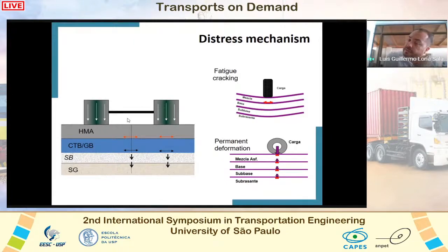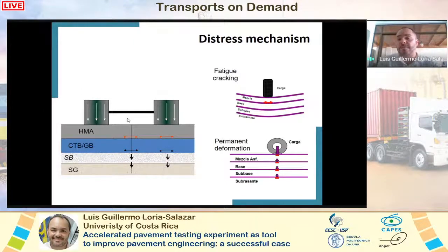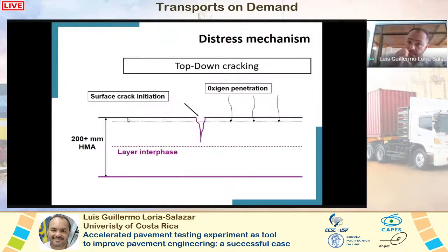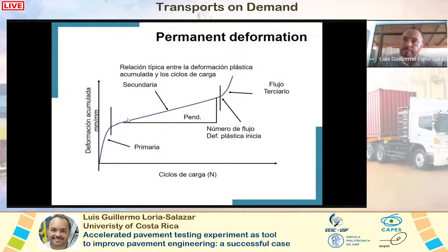We know the various distress mechanisms for fatigue cracking. Basically the bottom-up one, when you have the maximum strain at the bottom of the hot mix asphalt layer. For the cement treated base, you might also have the analysis of the tensile stresses at the bottom of the CTB, and compression stresses for the granular materials and the subgrade. Top-down cracking is initiated by oxygen penetration, oxidation. Weakening analysis or not, in our case we didn't do that, but we analyzed a lot of permanent deformation.